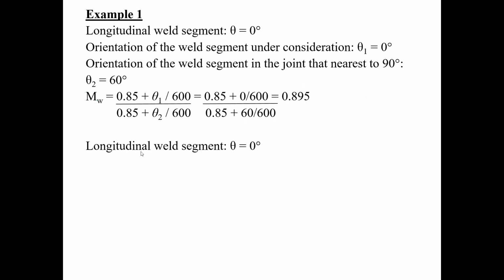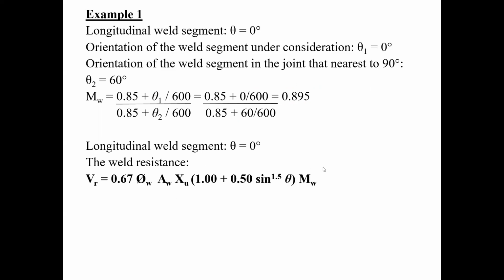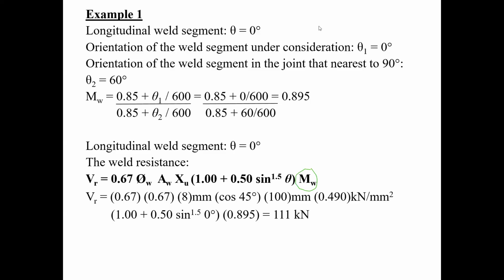So that's that. Now, the longitudinal weld, theta is equal to 0. Now for the weld resistance, here's my equation. I've already calculated the values of Mw for both orientations. So now, I want you to realize this is the size of weld. I can use either the cosine of 45 degrees or the sine of 45 degrees. Why do I do that? Because if you remember from your trigonometry, if this is 8 millimeters, the length of the member is either the sine or the cosine of 45 degrees.